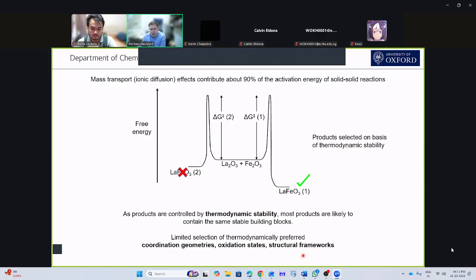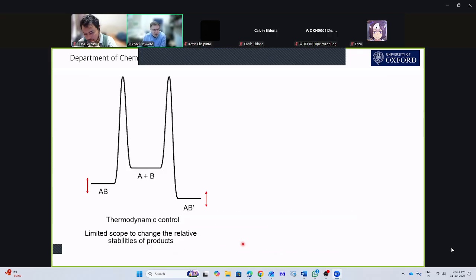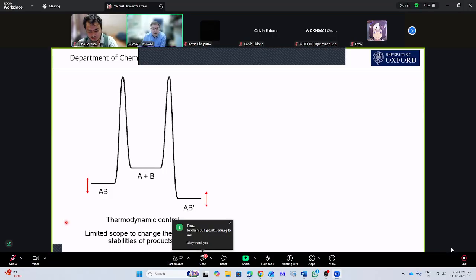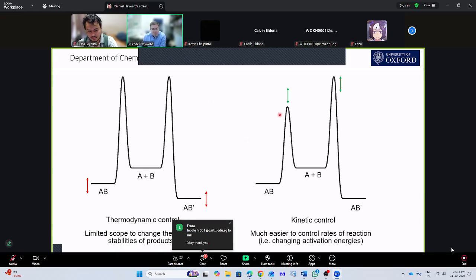So how can I think about getting around this? Well, one thing I could try and do is I could try and change the relative stabilities of my competing phases. Now that's extremely difficult to do. So you could try and change the relative stability of our product phases by changing pressure or maybe changing temperature, but that's really challenging. A better way of approaching this, or a simpler way, is to realize what I want to do is actually change the activation energies. And this is what we do in chemistry all the time.